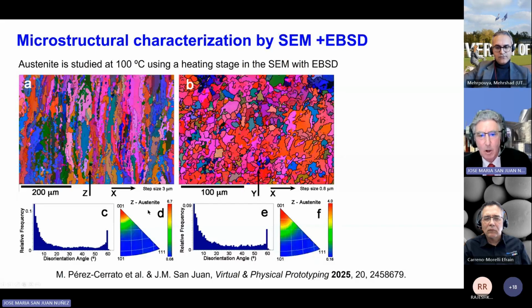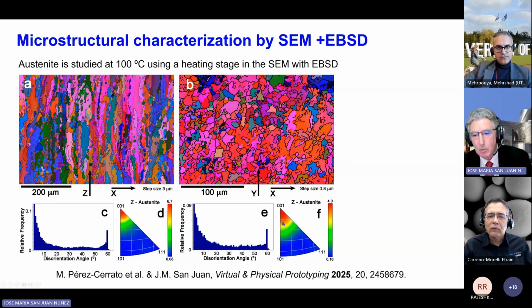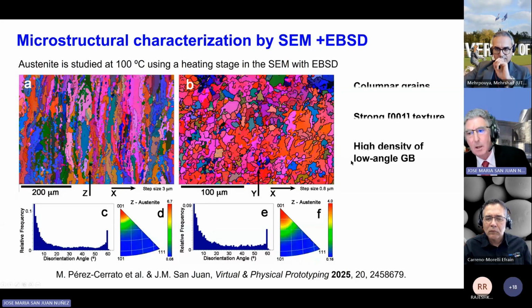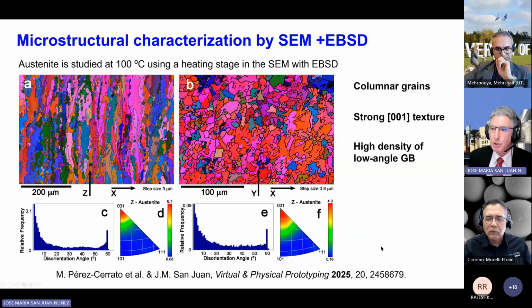And this texture can be seen also in a top view from the upper part of the material after drawing. This is a key axis because the columnar grains are moving up to the surface. And then we can also confirm the texture of the columnar grains towards the upper part of the building direction. In the middle of these columnar grains, there are plenty of subgrain low angle misorientation boundaries. And so we can conclude that during laser powder fusion in these alloys, we obtain columnar grains with a strong 001 texture and a high density of low angle grain boundaries because of the rotation of these columnar grains with respect to the others.